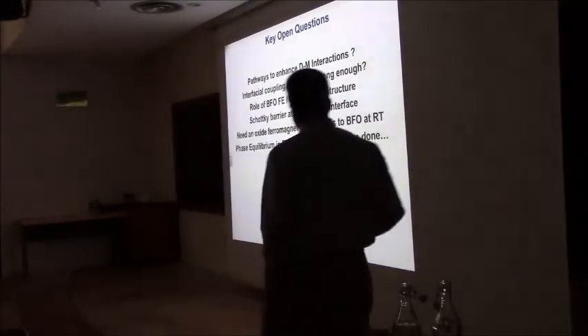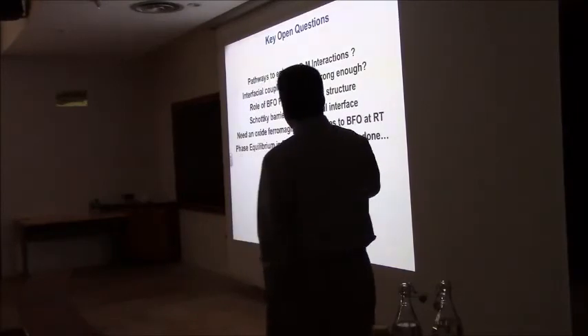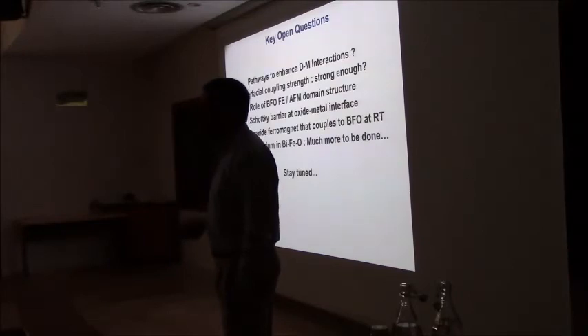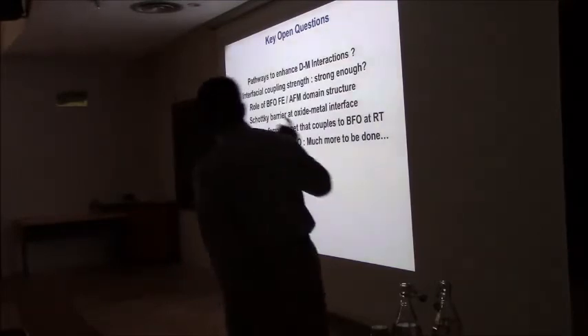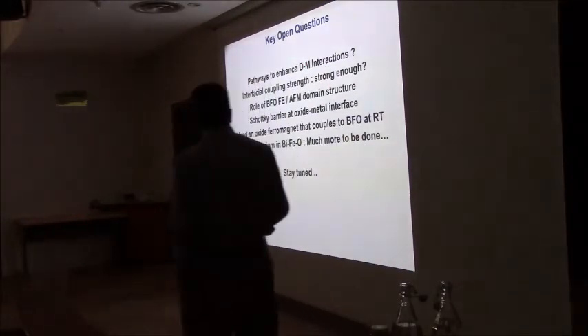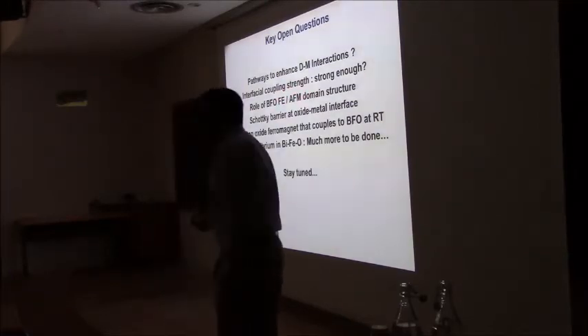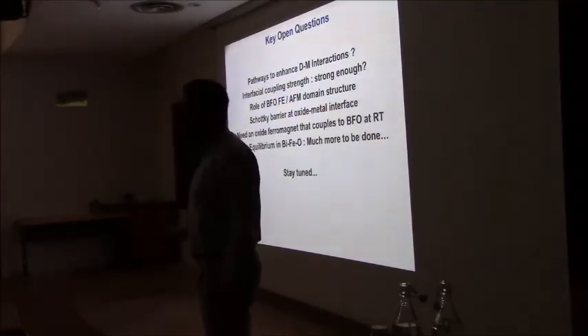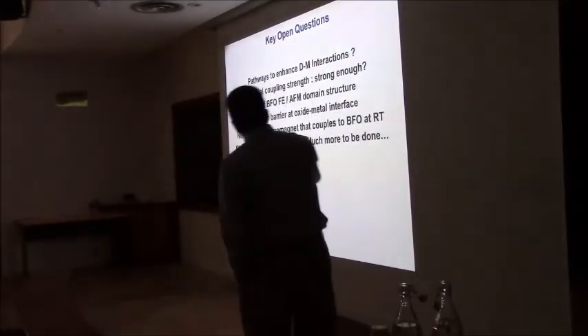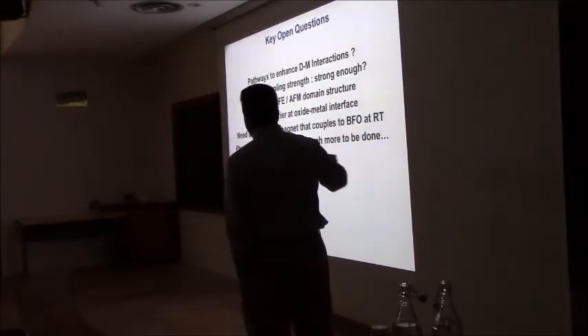Okay, what are the open questions? This is perhaps the most important slide. How do I increase Dzyaloshinskii-Moriya interaction? Good challenge, not obvious. And we'll finish up with some suggestions for tomorrow's talk. Is it strong enough, or is the nature of the coupling good enough? What is the role of the ferroelectric antiferromagnetic domain structure? It's not trivial to image or look at the antiferromagnetic order. You can use linear dichroism-based measurements. Perhaps the most difficult one is the Schottky barrier between the cobalt iron and the oxide.